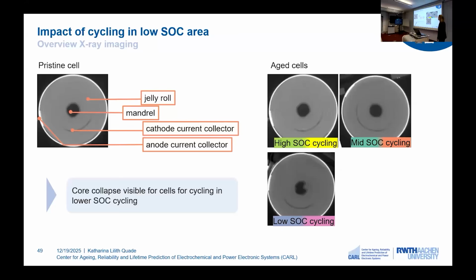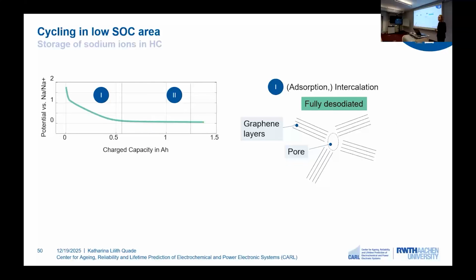And for low SOC cycling, we can see that the mandrel is shifted inward, the layers are significantly shifted, and we can see a so-called core collapse. To understand this better, we need to have a look at the sodium storage mechanism in hard carbon, because our anode is not graphite, it is hard carbon.